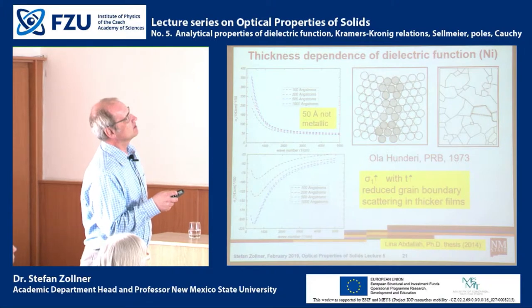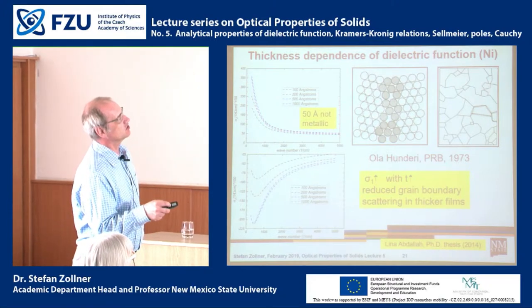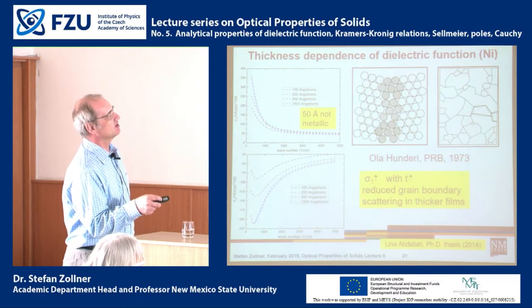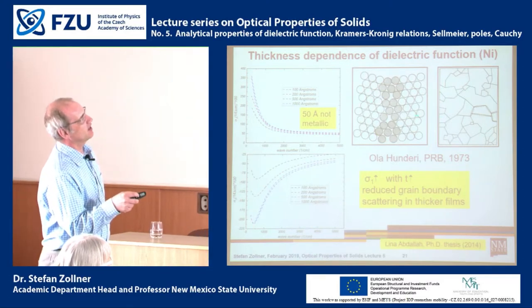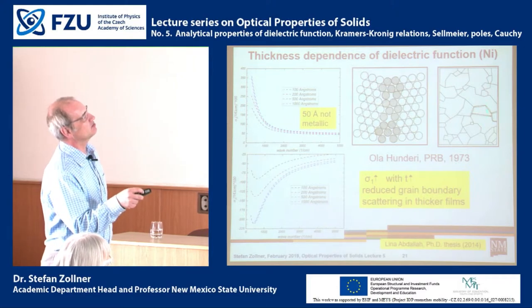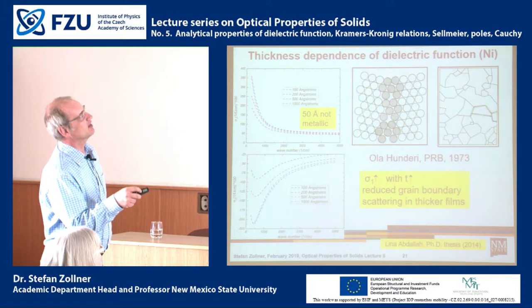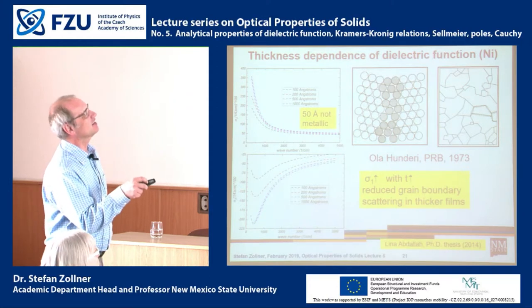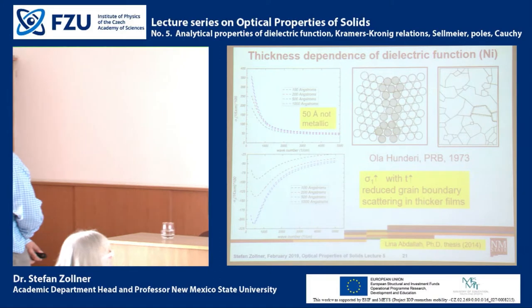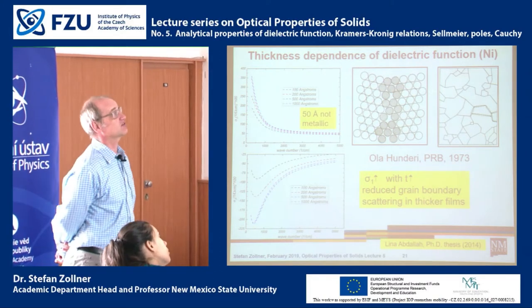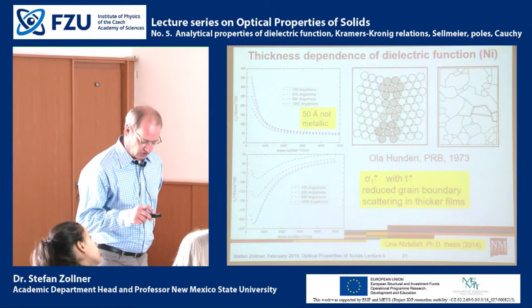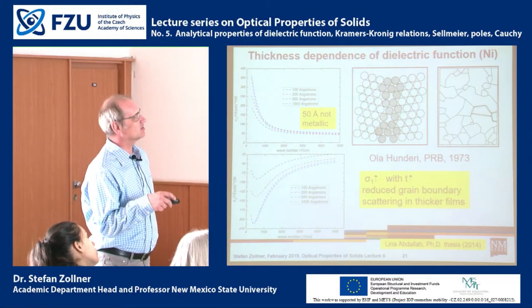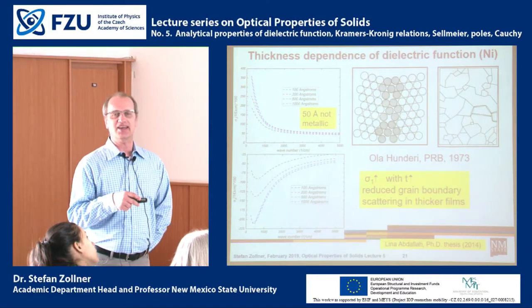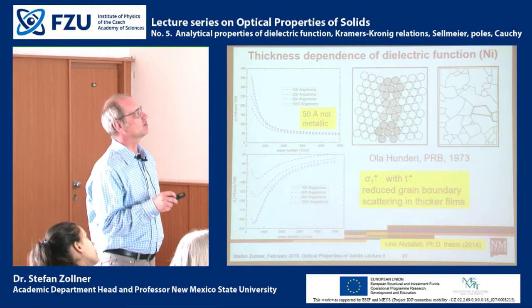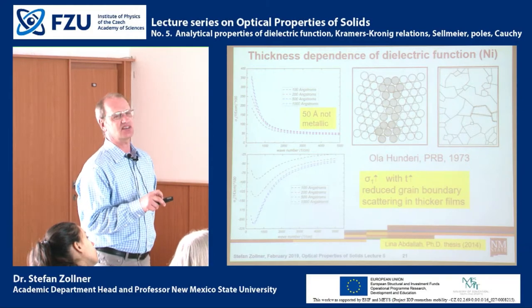And so in these pictures, there is work by Ola Hunderi, also from some years ago, where he explains the scattering in polycrystalline metals from grain boundaries. There may be some electrons which are in the bulk of the material, and the electrons which are at the grain boundaries may have different mobilities and therefore also make a different contribution to the dielectric function. So these metals tend to be rather dirty, so we cannot really get them as clean and as perfect as silicon, and therefore we see a lot more variations in the optical constants of metals.